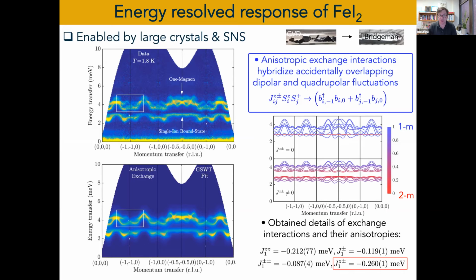Yeah, that's a very good point. What we can tell is that the phonons are at a higher energy than our magnons, and we don't see a direct coupling. There is no matching phonon at the energy of our magnetic excitations. There are other materials in the same series of iron dihalides: iron bromide, iron chloride and iron fluoride. These materials were studied by many groups in the 1980s, G. Shirane and Bob Birgeneau and company. I think in FeCl2, the magnetic excitations are higher in energy and they couple directly to a phonon. In that case there is a hybridization with the phonons that is resonant because they have the same energy. In this material, we believe that although the coupling should be strong, it's a less visible effect because the excitations are so low in energy in this system. You see, we are below 4 millielectronvolts.